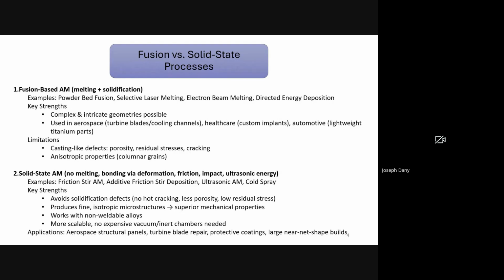The biggest advantage of solid-state additive manufacturing is that there is no melting, as I said earlier. We avoid solidification-related effects entirely. So no hot cracking, less porosity, and lower residual stresses. The microstructure usually comes out finer, equiaxed, and isotropic, giving us better mechanical properties overall. Solid-state methods also open the door to using materials that are usually unfriendly to fusion, like non-weldable alloys that would otherwise crack if we try to melt them.